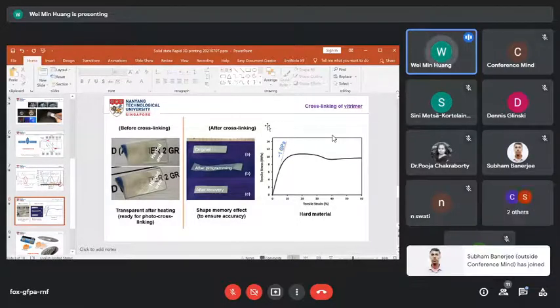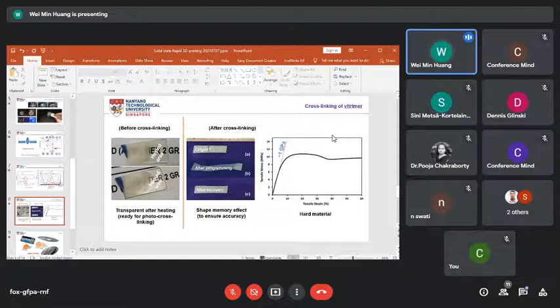The second thing is the shape memory effect after cross-linking. As shown over here, this is the original shape. If you heat up and stretch it, yes, it maintains this shape, but if you heat up again, it fully recovers its original shape. So it has a very good shape memory effect, and therefore we can make sure that the material is able to maintain the shape after removing the uncross-linked part.